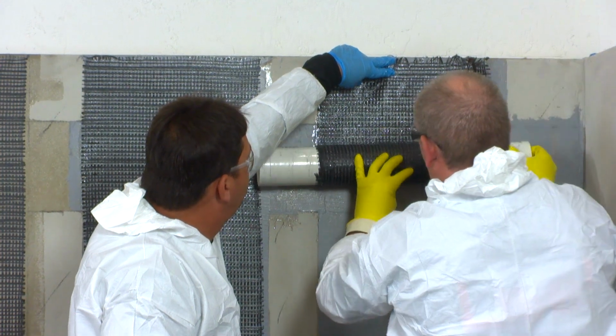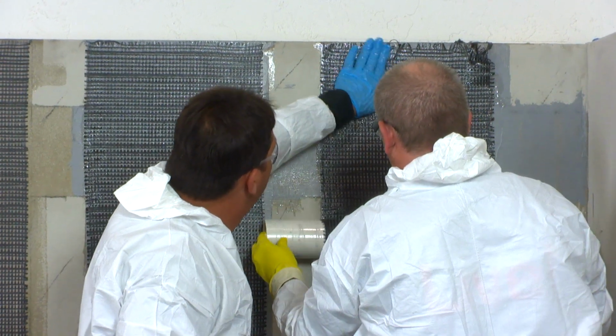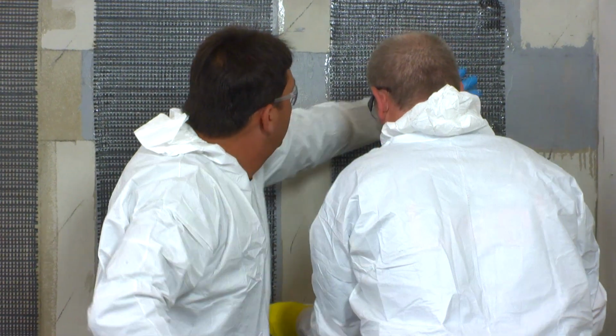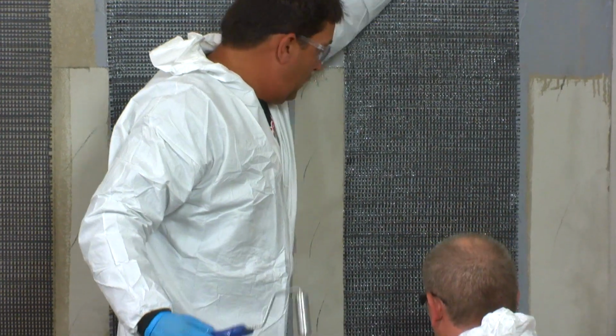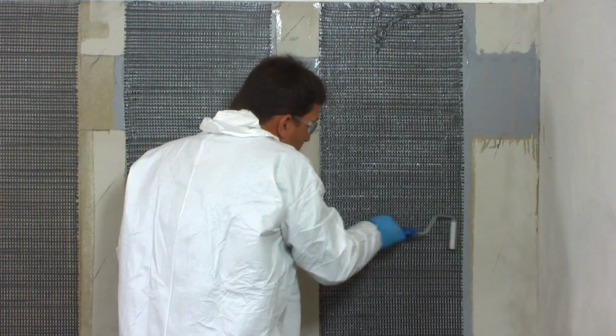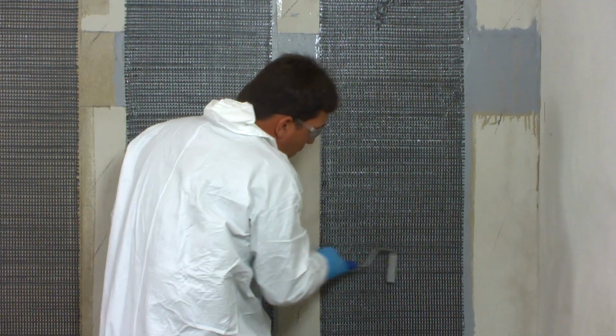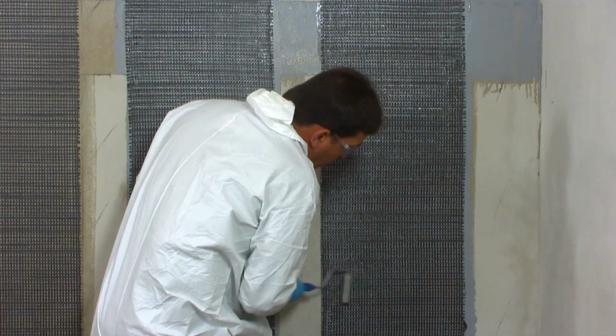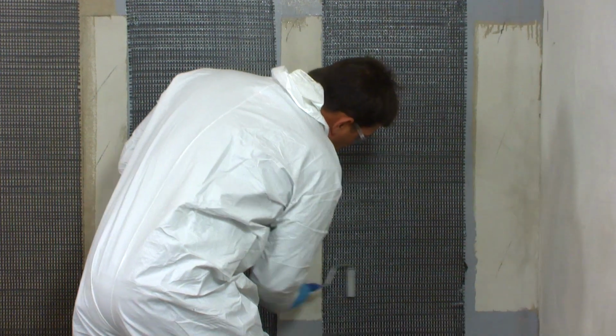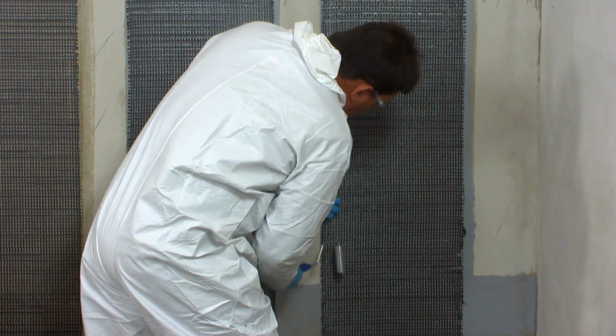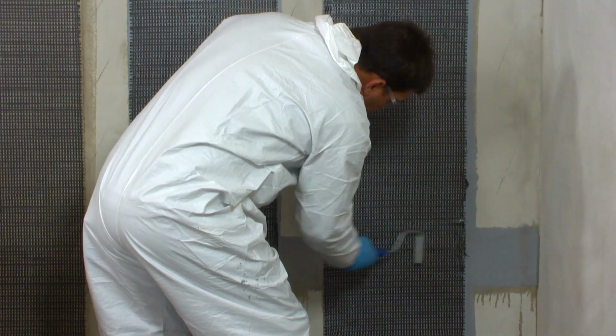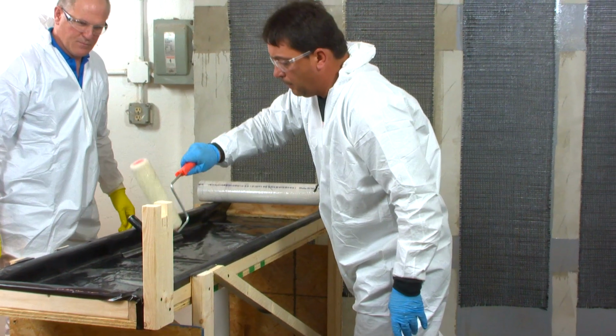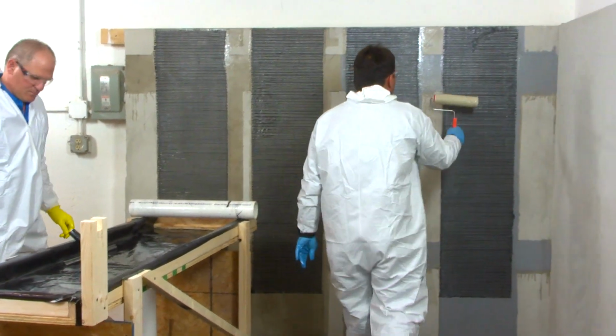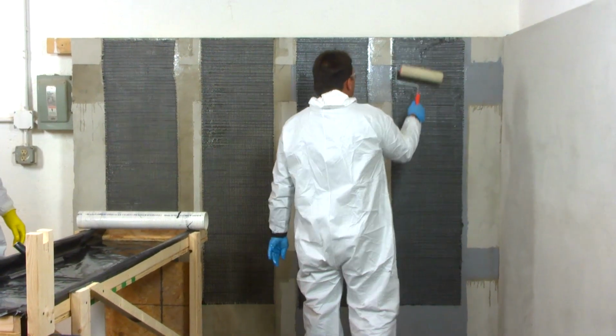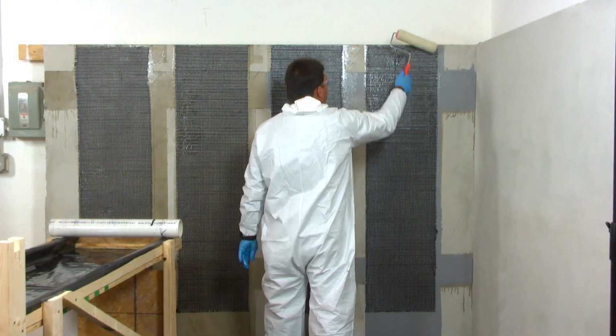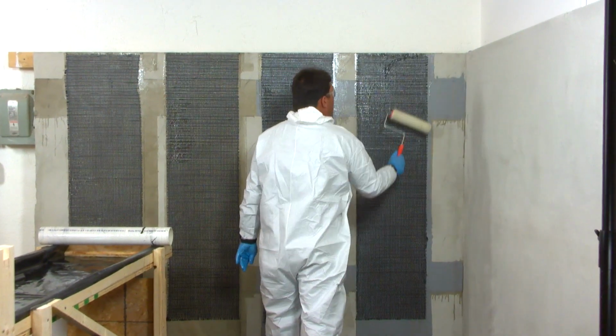This ensures that the fabric remains on a straight plane by pulling the material as tightly as possible without having it slide. Once the fabric is installed onto the substrate, follow up by using a ribbed roller to ensure the removal of any air pockets trapped beneath the fabric, which could weaken the overall system. Place an additional coat of MapeWrap 21 by roller until the installed fabric shows a glossy surface, and then use the ribbed roller again as often as needed.